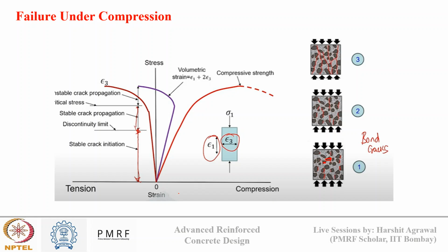Now, if we see this in terms of strain profile, the longitudinal strain, epsilon 1, represented by this red line, shows a steady increase in the first two stages, crack growth and crack propagation. However, it then shows an exponential growth in the last phase, when these cracks are propagating and finally connecting to form a failure plane. The lateral strain shows a very small increase in the initial two phases, but a drastic increase in the final phase when the cracks are already getting connected.